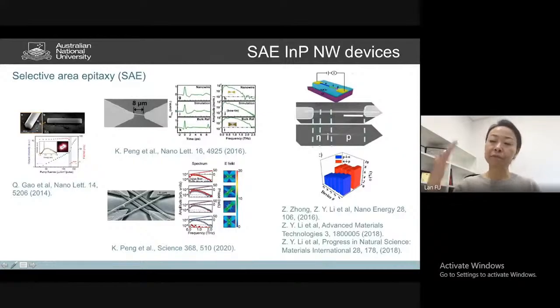And during the growth of the indium phosphide, we can introduce different doping. Silicon and zinc create N-type and P-type doping during the growth, and then we can contact them, making a single nanowire solar cell. You can see this is the electron beam induced current, which reflects the built-in electric field of the nanowire. You can see this EBIC contrast from the measurement, showing that we have achieved a built-in electric field in a single nanowire. And by designing the length of the field and so on, we can enhance the solar cell performance. We have a few publications in this area, and if you're interested, feel free to have a look.